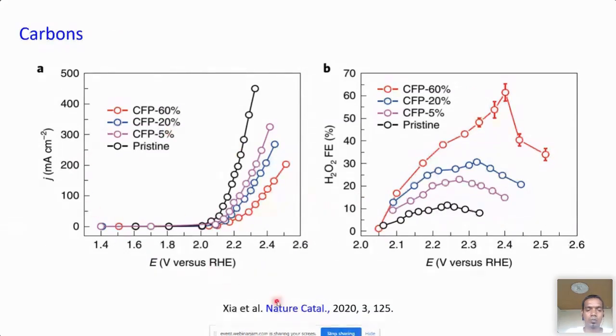This is recent work by Xia, published in Nature Catalysis, where they took carbon fiber paper, a very common substrate electrode used in electrocatalysis, and coated it with different percentages of PTFE, Teflon powder. They found this increased the hydrophobicity and trapped oxygen inside the layer, which helped increase the selectivity for hydrogen peroxide production. They achieved selectivity as high as 65% at 2.4 volts with simple carbon fiber paper.